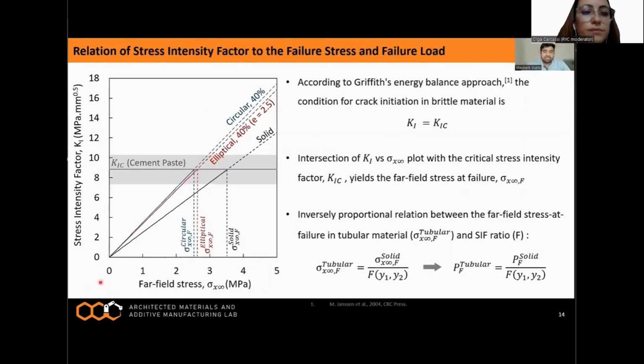Now here I'm showing the plot of stress intensity factor and far field stress in the solid, and in the presence of the tubular void of circular 40% and elliptical 40% with the aspect ratio of 2.5. So in a brittle material such as cement paste, a crack initiates when the stress intensity factor becomes equal to the critical stress intensity factor,